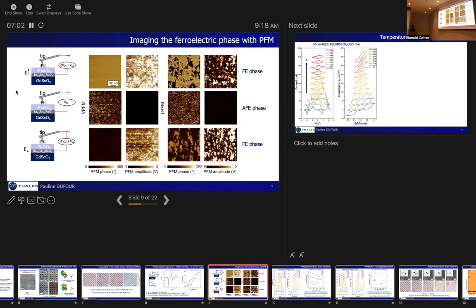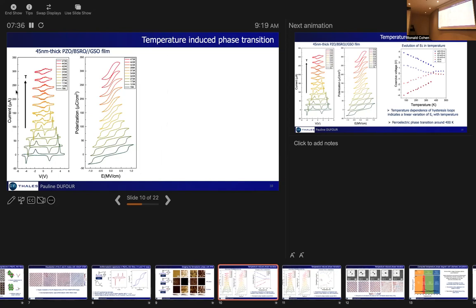We intended to reconstruct the polarization in 3D through vector PFM. Unfortunately, our attempts were quite unsuccessful so far, probably because of the loss of the ferroelectric memory as soon as you go back to the antiferroelectric phase. But we think that PFM could be a promising technique to investigate more precisely the polar state, maybe in thin films that present only one single structural domain, instead of our films that have several variants and make things more complicated. So now we turn to the temperature-induced phase transitions.